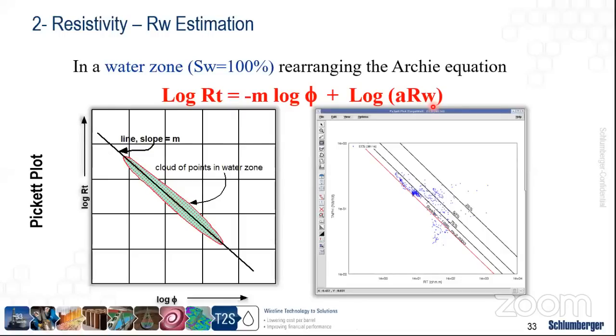So we made 2 assumptions. First of all, we made an assumption that A is equal to 1. And then we went to the water zone, assumed that it's 100% water filled, and there's no residual oil, or there's no oil in this part of the reservoir. And then we plot the points, and based on the slope and intercept, we can assume the RW. This is the first approach.